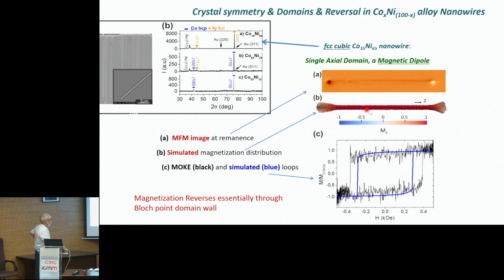This is a micromagnetic simulation, and this is an experimental hysteresis loop, this noisy loop, obtained by the magneto-optic Kerr effect that we have in the laboratory. So you see this behavior, these large Barkhausen jumps, reminds one of the magnetic bistability of the microwires. In fact, when we apply the magnetic field anti-parallel to the magnetization here, we will have a kind of Bloch point domain wall that moves very fast from one end to the other.